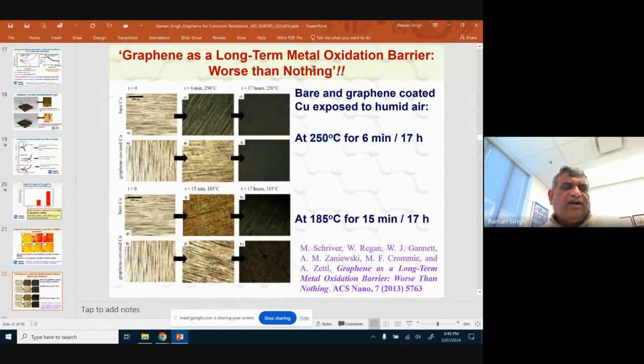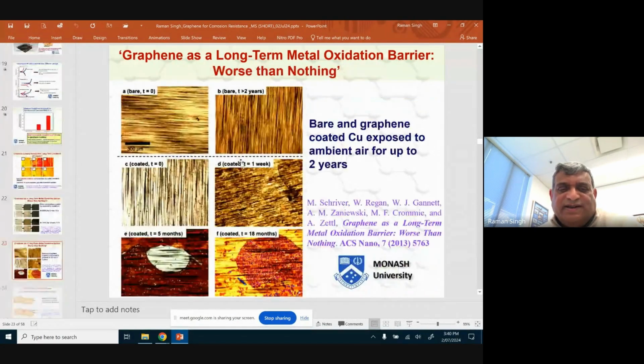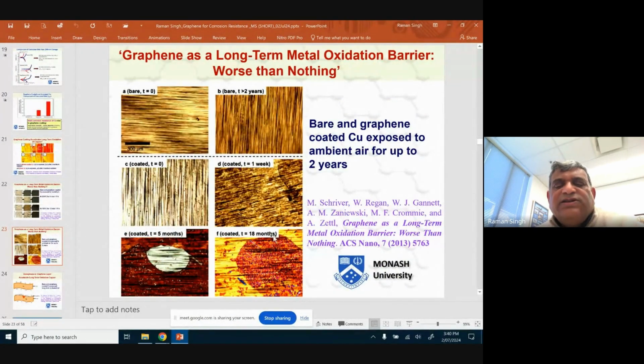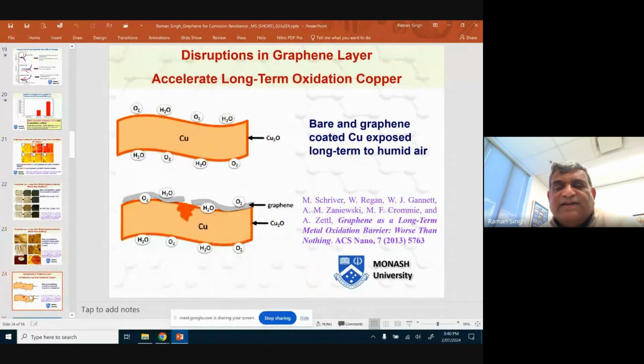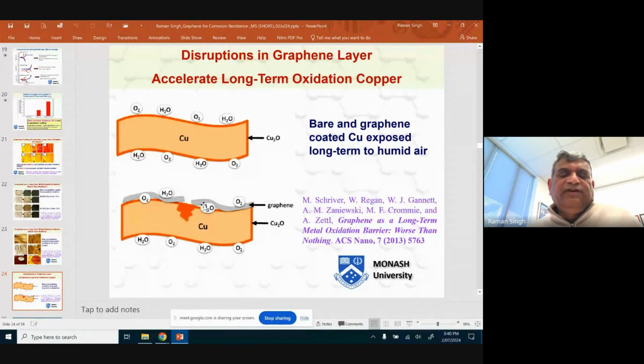So what was going wrong? The thing that was wrong in their study was that they were not using good quality graphene. As a matter of fact, wherever the quality of graphene was good, corrosion resistance was still good. And in fact, they said that this lack of corrosion resistance due to graphene was happening because of disruptions in the coating. Wherever the coating was discontinuous, corrosion was happening at a high rate there, which was not surprising at all.